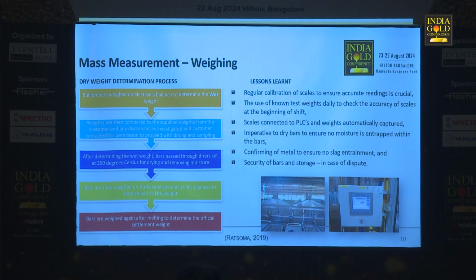Also, what we've noticed is that the calibration of scales, that's why we had to go for 17025 accreditation on mass metrology, which means we've got in-house skills to make sure that every scale gets to be calibrated at certain sequential intervals, and every day there's a process of calibration to make sure that we don't make an error. Our error margins are very low, so we have to have that precision. All the scales, like for example, this one, as you can see, they are linked to PLC. That's an investment we decided to make to avoid handwritten errors. Sometimes those last significant values, if they're not correctly written, can end up to errors and gold losses in a refinery. So everything is calibrated, and then it's looked at.